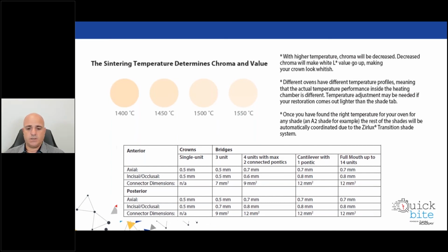And sometimes 20 degrees will affect your chroma, as you see here. So for example, if it's a very low temperature of 1400, it becomes more opacified and higher in chroma. 1450 is where you get the more appropriate result, but then it's less opacified. And the hotter it gets, you can see you're losing all the chroma, but what else are you getting? You're getting a lower value, which may contradict the shade that you're trying to achieve. So understanding and calibrating and purging is how you really truly get control of your zirconia outcomes.